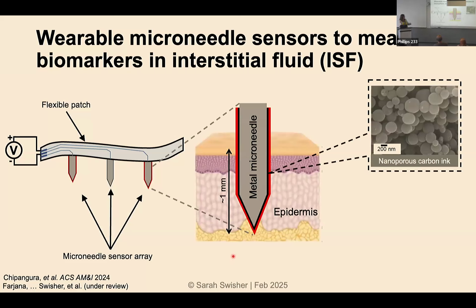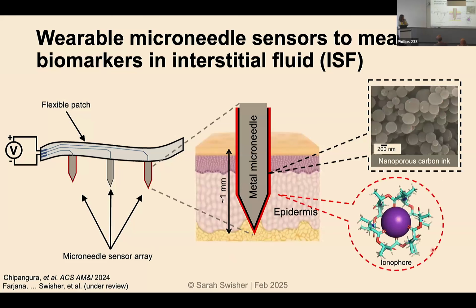We want to make this into a soft wearable patch that then has these rigid functionalized microneedle electrodes. They have a nanoporous carbon layer and an ion sensitive coating on the outside. We want to use those to do long-term continuous measurements of biomarkers in the interstitial fluid so that we can provide information for triage for trauma care.